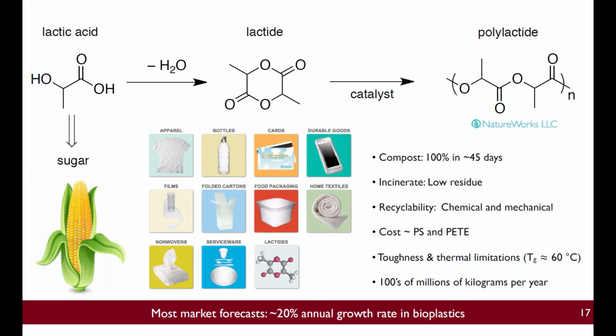Let me tell you about probably the most successful bio-renewable, bio-based polymer out there. This polymer was actually developed at Cargill originally here in Minnesota and now is under the name NatureWorks. This is called Polylactide. Probably many of you heard of Polylactide. For those of you who haven't, this is an aliphatic polyester that comes from sugar. Ultimately, corn is fermented to give lactic acid. The dehydration of lactic acid gives lactide, this cyclic dimer right here. And through a ring opening polymerization, you can generate this aliphatic polyester.